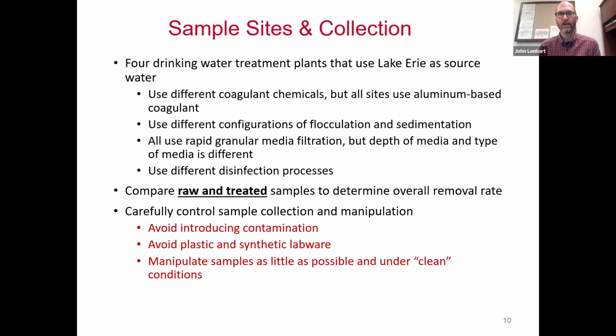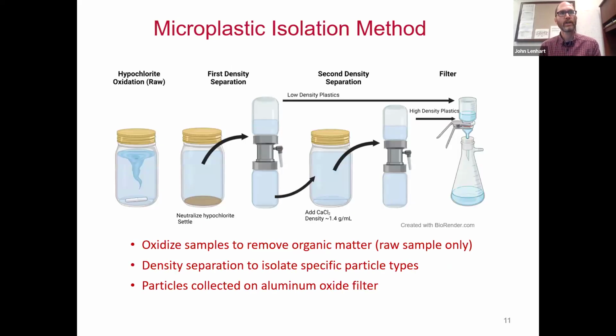So we use clean methods as much as possible. We avoid using plastic or any other synthetics in the laboratory spaces, and use glass and metal for any sort of material handling. Just real quick in terms of how we isolate the plastic: we collect the samples in, again, a glass jar. We do an oxidation step if the sample is coming from the lake, because we need to oxidize the organic matter associated with that to remove it, because that interferes with subsequent processing.